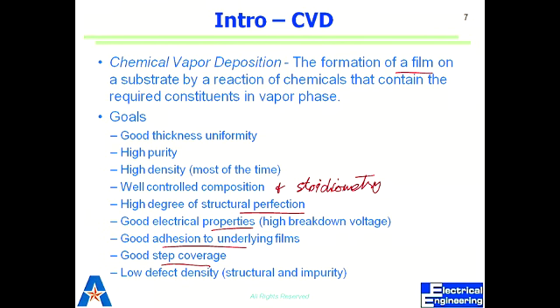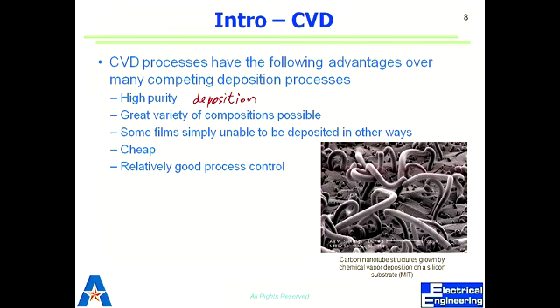Good adhesion, good step coverage. It should cover everything and shouldn't have too many defects in that. So how do we achieve those? This CVD advantage over others, it gives you highly pure outcome, because the product that you get is the result of a reaction, so you are making those reactants come to the surface of your wafer. So what you get is very pure right there. It gets made up right there and gets attached on the surface. Unlike PVD, where your source is away from the wafer, and you melt it and you let the vapors travel to the substrate, right? So we'll see that in PVD.